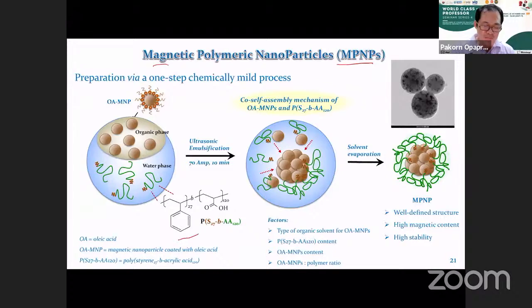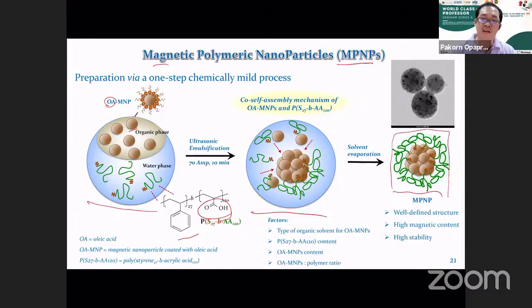We use a copolymer of polystyrene and acrylic acid here as the polymer matrix. Then we prepare small-size magnetic nanoparticles and stabilize them with oleic acid. During the formation of the polymer particles, we disperse these small magnetic nanoparticles into the droplets of the polymeric particles. As a result, we have polymeric particles that disperse very well in water and contain small magnetic nanoparticles inside, with very high magnetic content and very high shape stability.